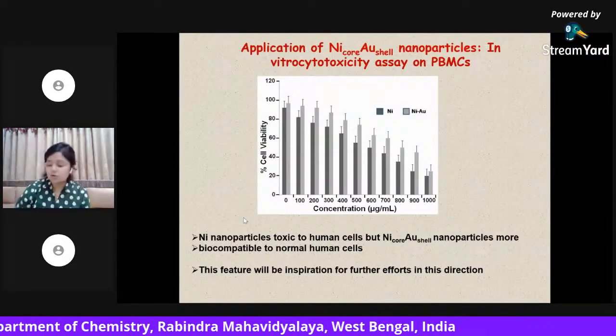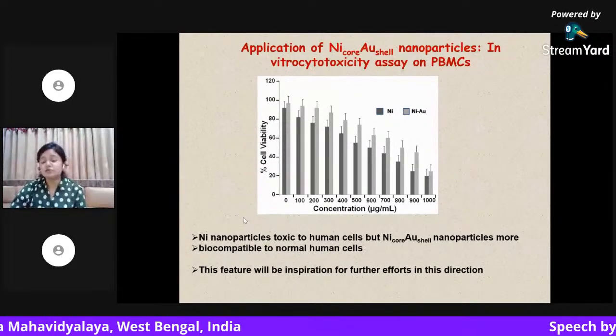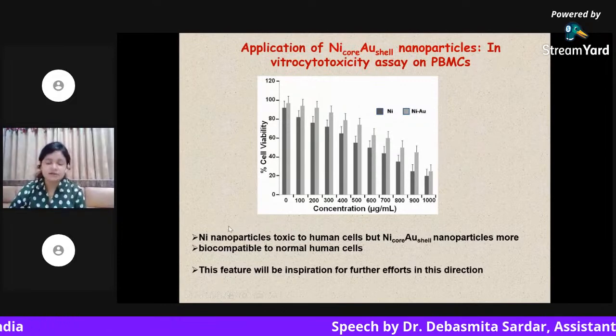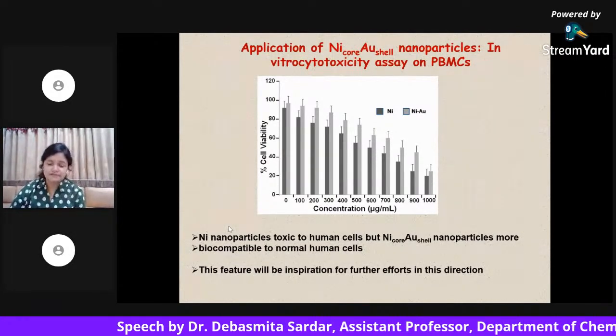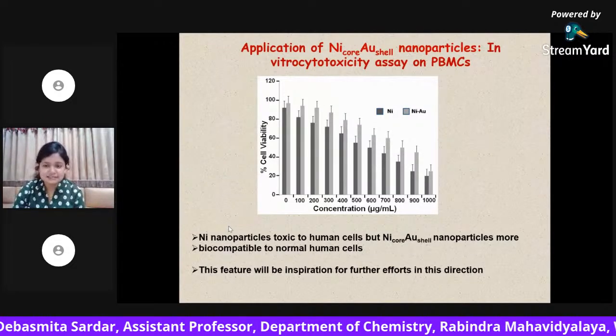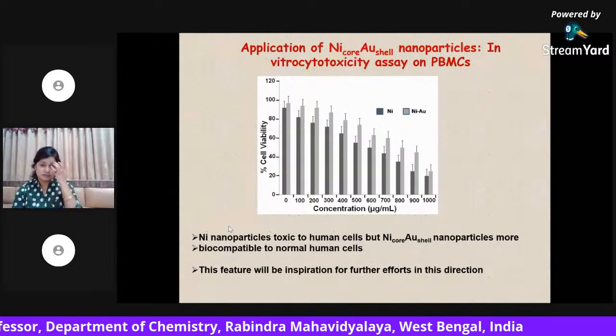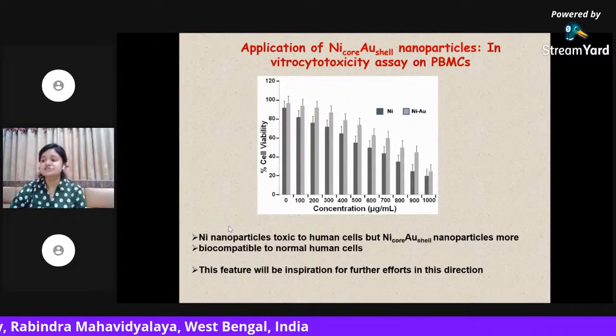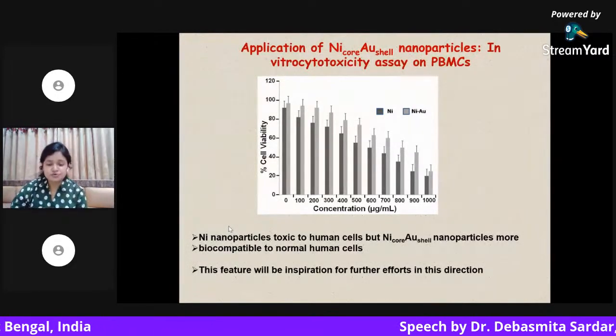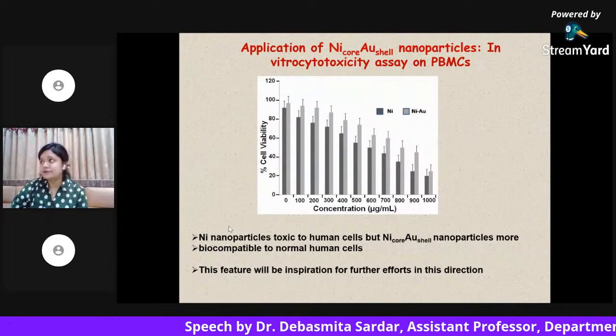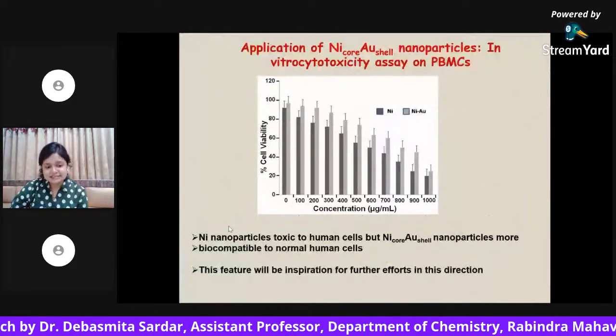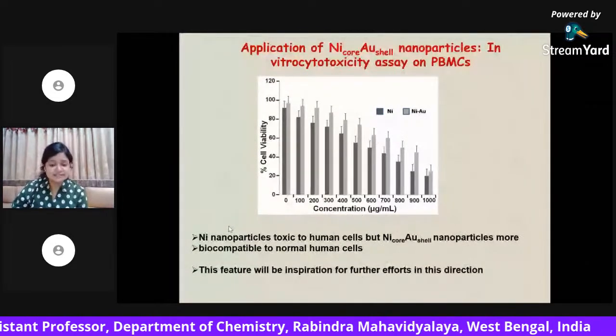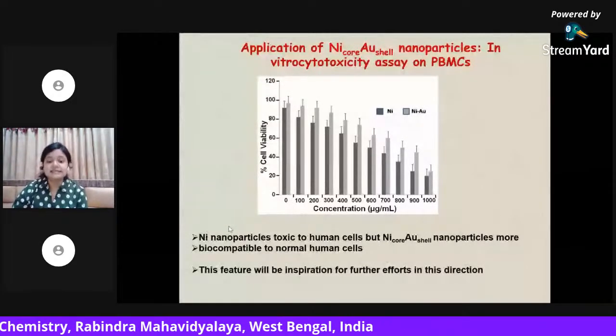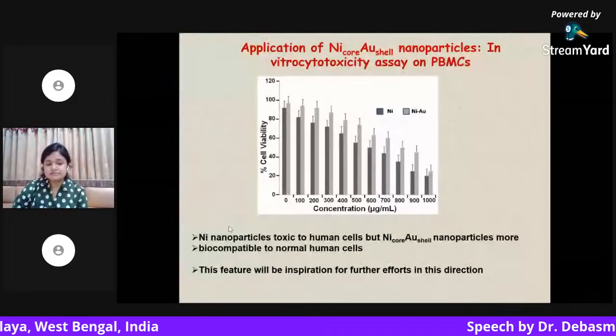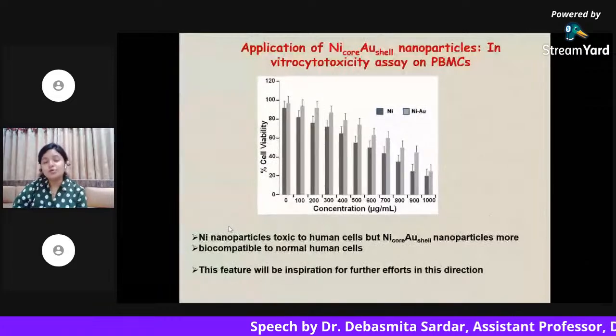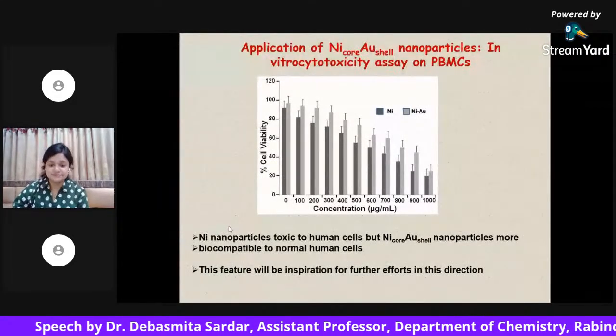And this is the application of nickel gold nanoparticles, where we have injected these nickel gold nanoparticles in normal human cell and in normal blood. After doing the process, this is named as in vitro cytotoxicity assay on PBMCs. Basically, it was a collaboration work with some physiological department of Calcutta University. So we have worked with real human blood cell. The result is that nickel nanoparticles are very much toxic to human cell, but the nickel gold nanoparticles that I have synthesized are not toxic, so they are biocompatible to normal human cell. So we can use them as a medicine.